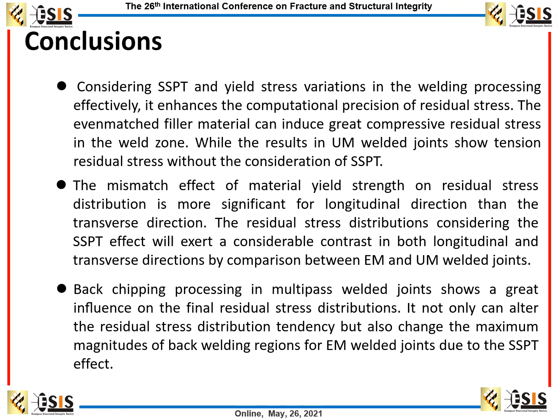The second point is that the mismatch effect of material yield strength on residual stress distribution is more significant for the longitudinal direction than the transverse direction. The residual stress distributions considering the SSPT effect will exert a considerable contrast in both longitudinal and transverse directions by comparison between the EM and the UM welded joint.